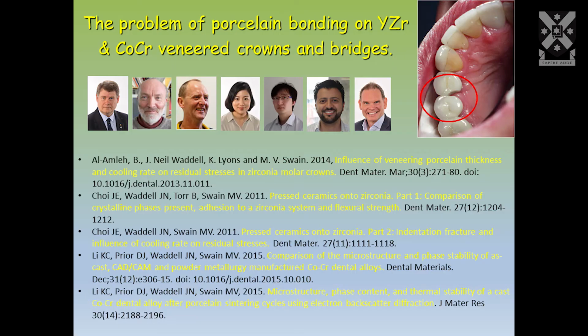Now, when we sort of found the answer to that problem, new problems were arising. And this was a chipping or failure of the bond of porcelain to zirconia substructures, and at the same time to cobalt chrome, which is a metal substructure. So what was happening was that the industry had been promoting the use of zirconia as a new material with CAD-CAM type manufacturing processes. And worldwide, reports were coming in that the porcelain was chipping off. At the same time, the gold price, the precious metal price, had gone skyrocketing up through the roof, and the whole world was switching away from noble-based alloys to cobalt chrome. And likewise, we were doing the same here. And we were finding problems with the veneering porcelains chipping away from it.